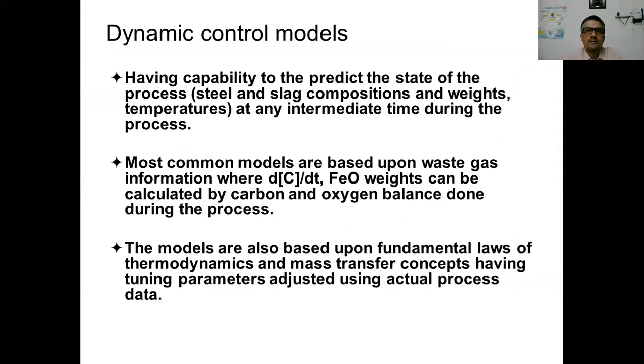Dynamic control models have the capability to predict the state of the process. That means the time-dependent values of the steel and slag compositions, their weights, as well as the temperature. The most common models now being used in steel plants are based upon the waste gas information: the decarburization rate, dC/dt, and FeO level. They can be calculated by performing a dynamic carbon and oxygen balance of the process from the waste gas data. People have also developed models based upon fundamental laws of thermodynamics and mass transfer concepts. A lot of literature is available on these fronts, and people may have a look at it.